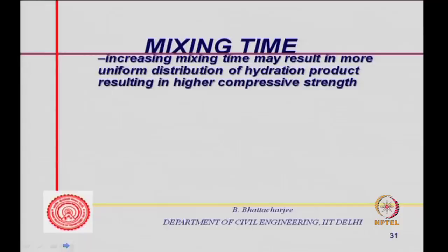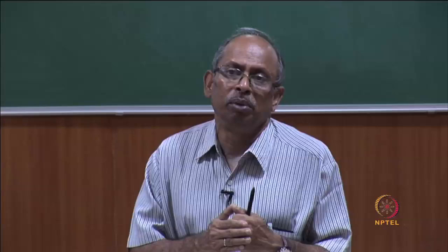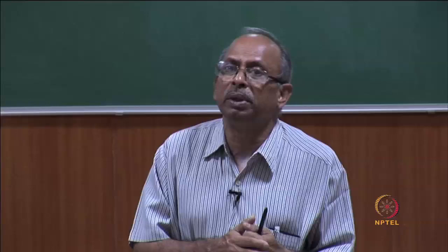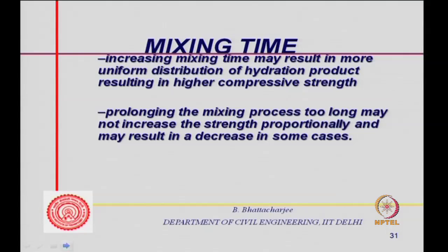But first of all, let us see why I need sufficient time, because increasing the mixing time may result in more uniform distribution of hydration product. It causes abrasion over the surface of the aggregate and therefore removes the hydration product, and some of it then gets further exposed to water. New hydration product would get deposited on top of the aggregates and so on. So, it actually causes a better dispersion and more uniform scenario, and therefore higher compressive strength. But there is a point of diminishing return.